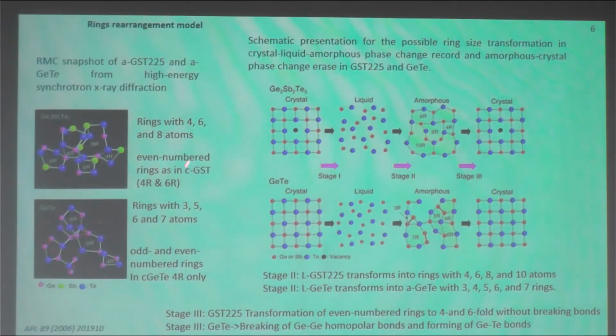If you compare the crystalline material, GST has in the crystalline state 4-fold rings and 6-fold rings. In crystalline GeTe, they have only 4-fold rings. Based on the local structure of the amorphous state, one can propose a transition model from the amorphous to the crystalline state, and it happens in several stages. If you start at the crystalline state of GST225, then we can go to the liquid state, and then it amorphizes after high cooling.